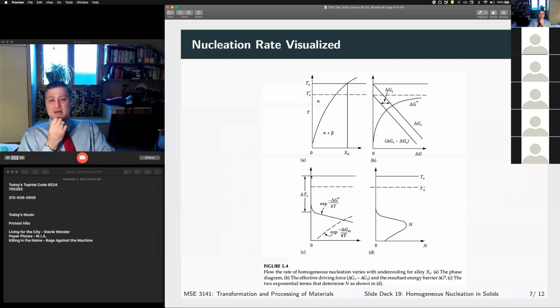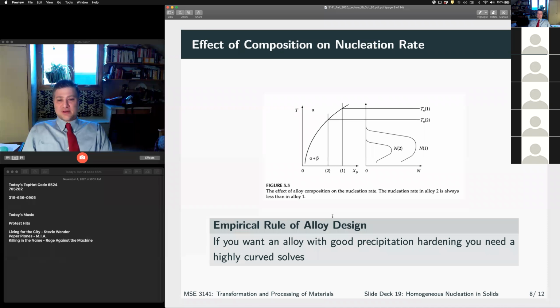And so at high temperatures, we have a very small bulk free energy, so our G star is large. As we get to larger and larger undercoolings, our G star decreases, right? And we have a larger and larger driving force for the transformation. But as our temperature drops, we have much less mobility, right? So this gives us a peak in our nucleation rate. There's very low nucleation up here because we have limited driving force. There's very low nucleation down here because we have limited mobility. But somewhere in the middle, there's this magical regime where we have a finite nucleation. Right? So those are the primary differences. Okay? And that's where we left off Monday.